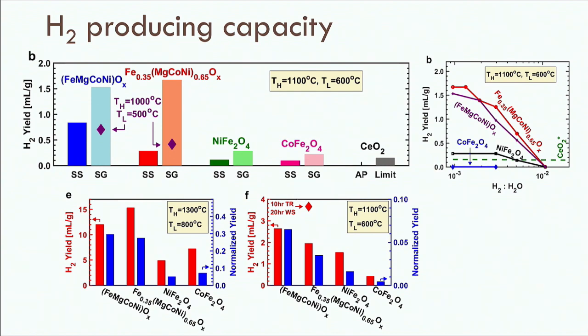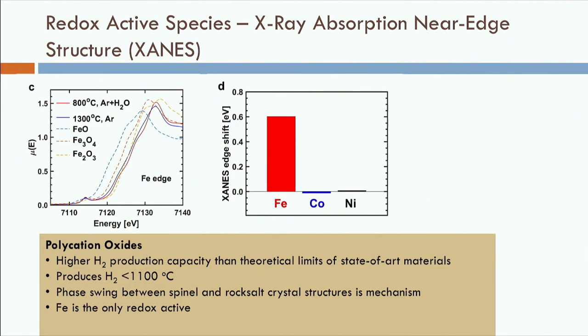The question is, of those cations that are there, iron, cobalt, and nickel, which one is actually redox active? Is one of them redox active, or all three of them redox active? The way to find out is to look at the X-ray absorption near edge structure. Here is where the oxidation level changes, shifting the core absorption of the electrons. And what we find, the bottom line, is that iron is the redox active species. Cobalt and nickel are redox inactive. What we're trying to find out is what cobalt and nickel are doing in this lattice, and we are still trying to figure this out.